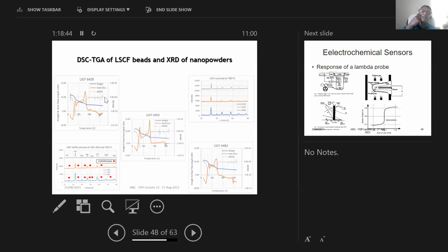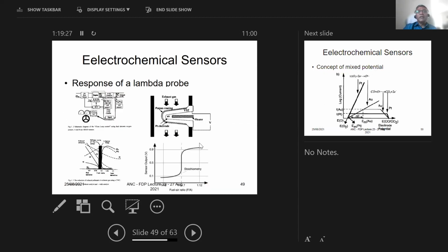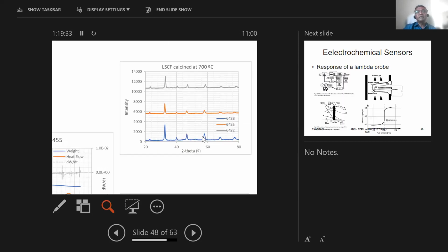Then we did the DSC TGA of these beads, 3 different compositions of LSCF. And again, what you find is that around 400 degrees Celsius is the temperature at which the fully oxidized product is formed, single phase product is formed. So irrespective of the cations that we ion exchange in alginate, the alginate process produces the single phase product at around 400 to 500 degrees Celsius as the calcination temperature. So these are the three different compositions that we produced. And again, these three compositions form a very nice single phase product from the alginate process.